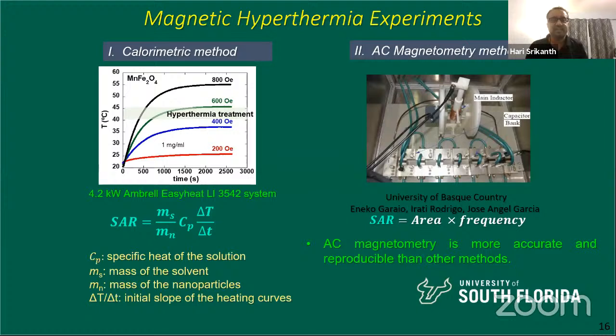If you don't, there's no need to overheat the particles. And of course, if you don't supply enough amplitude at the right frequency, you will not heat up at all. The saturation is because of thermal equilibrium between the particles and the surrounding tissue, okay? So you can tweak these conditions so that you can achieve the hyperthermia treatment window, and you can select these for different particles of different sizes by playing around with these conditions.